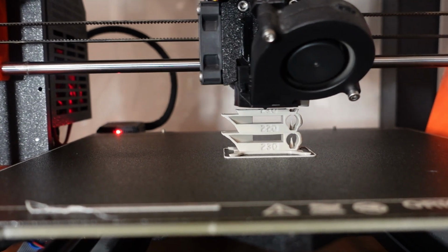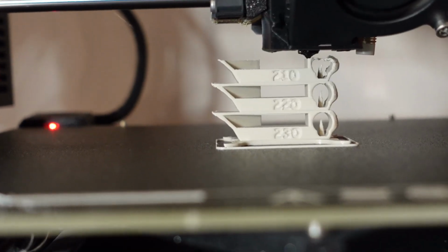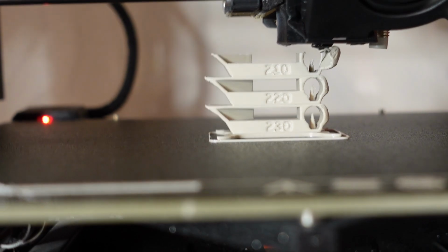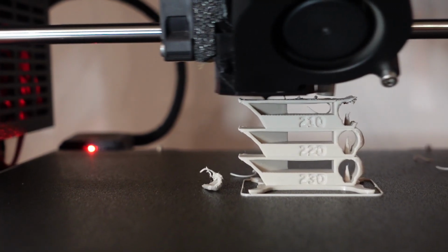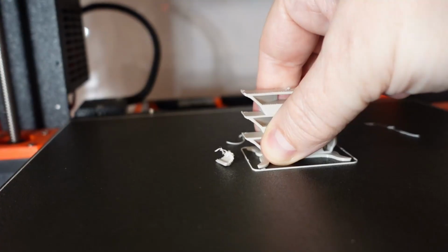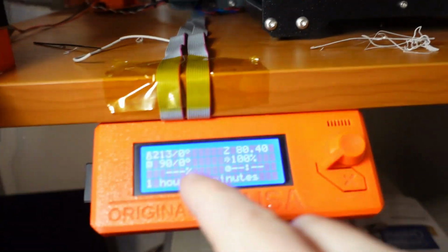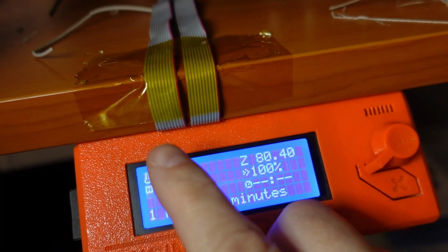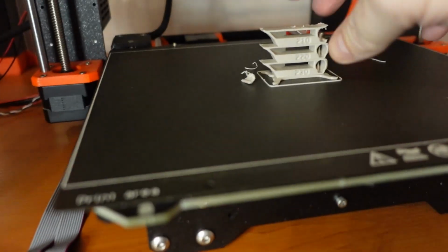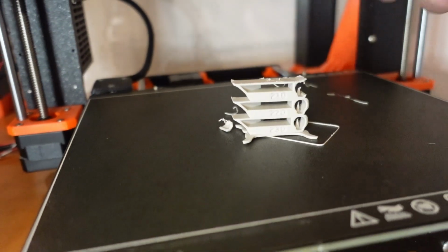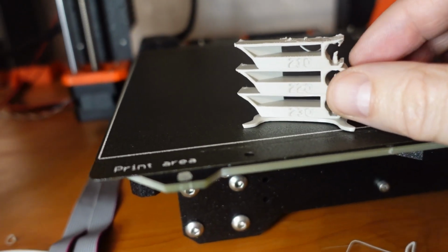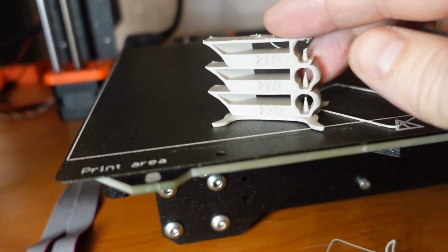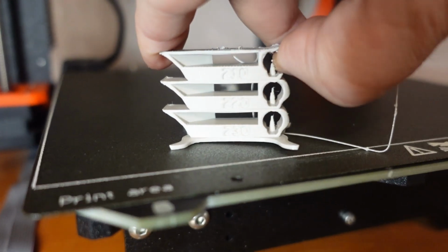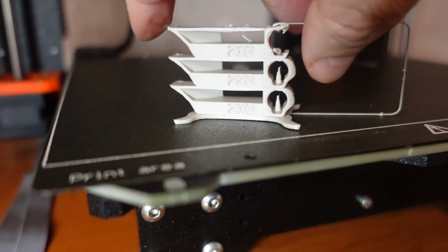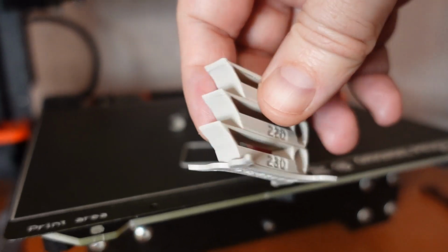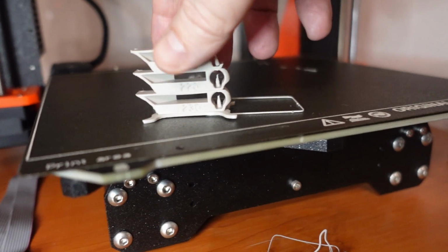At 210 degrees Celsius I noticed a problem, and I believe it is because of weaker layer adhesion, because maybe I'm using a hardened nozzle, at the lowest temperature part of it didn't stick too well. The material sticks well, but when the bed cools down it is very easy to remove. So as you can see, this temperature tower looks okay except for this part, which I believe is a weaker layer adhesion problem, but we will see that in the layer adhesion test.